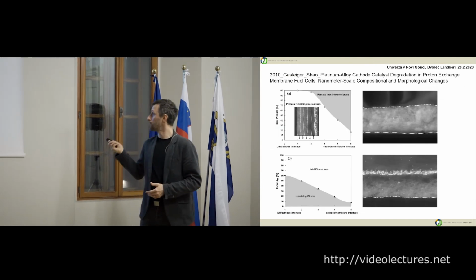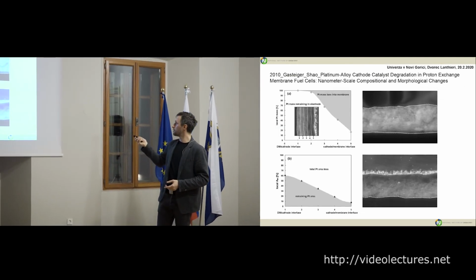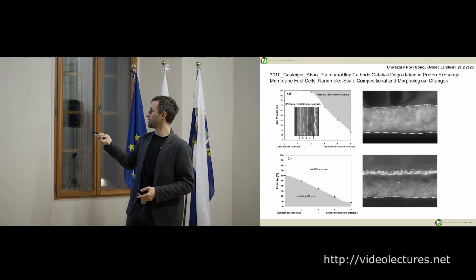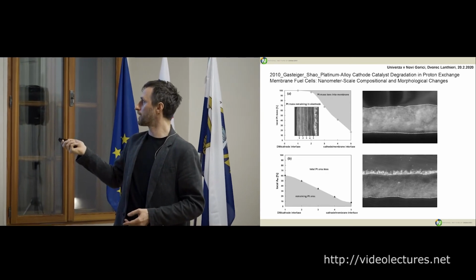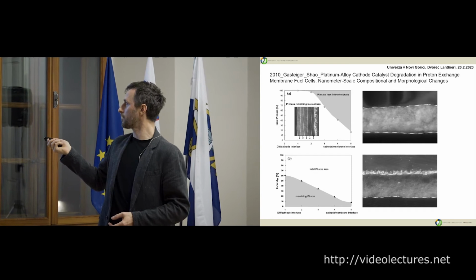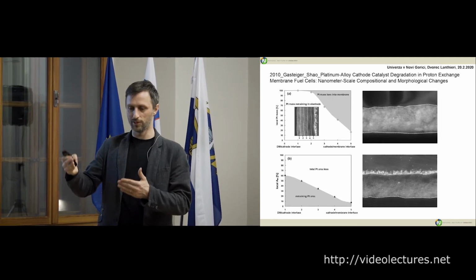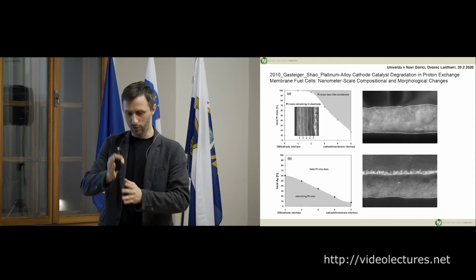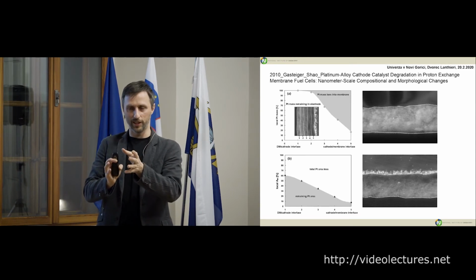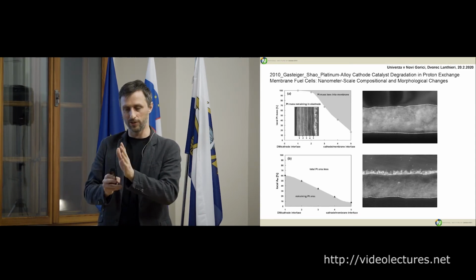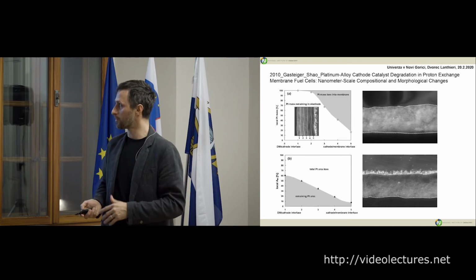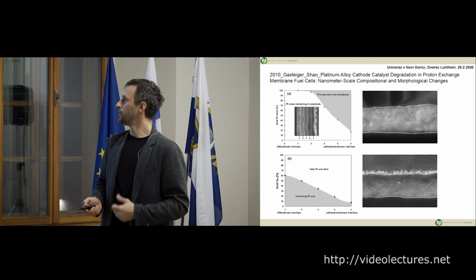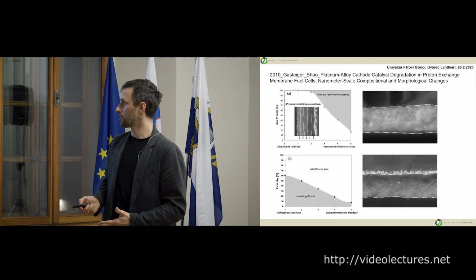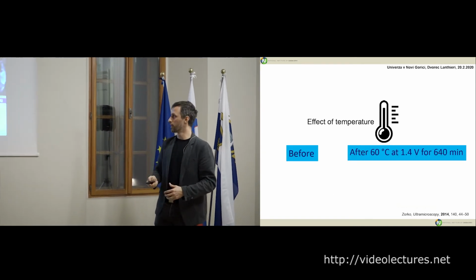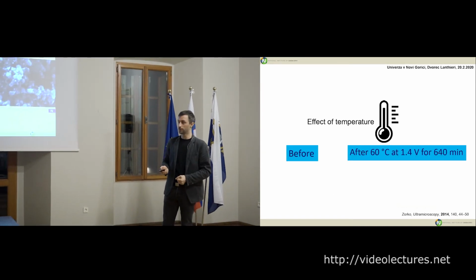What is interesting is that if you cut a fuel cell, and this is the membrane and the catalyst, the anode and the cathode, and this is the degraded one, you can see that in the membrane you have this line of platinum which is dissolving and coming to a certain point in the membrane, which is then getting reduced because of the hydrogen crossover. But it's kind of similar to what we saw in our experiment. You can do degradation with higher temperatures. I will not lose time here, but what you basically see is a lot of agglomeration and coalescence because of the carbon corrosion.